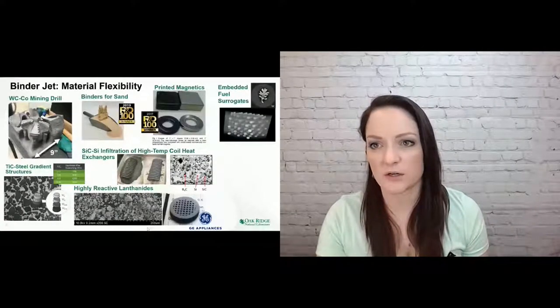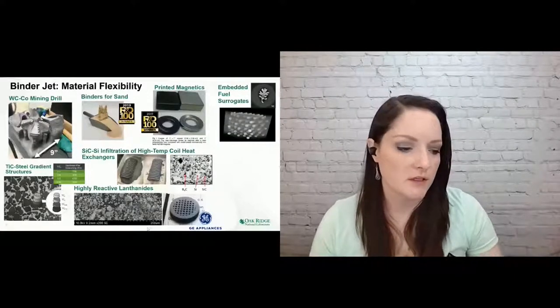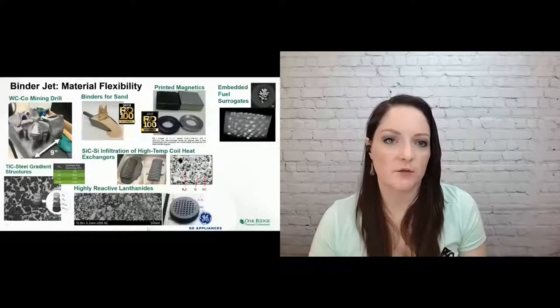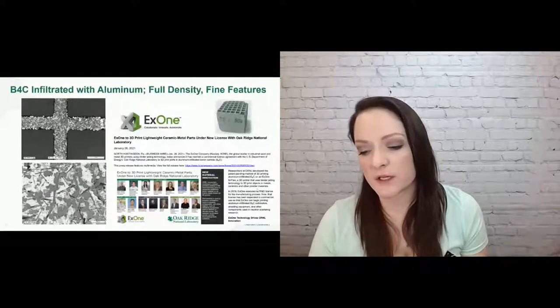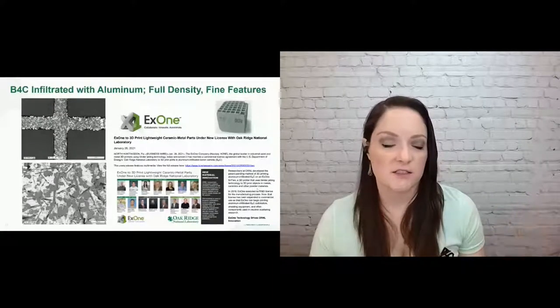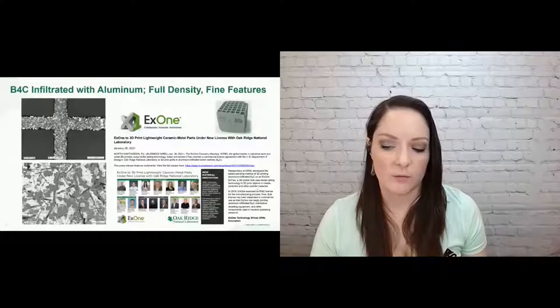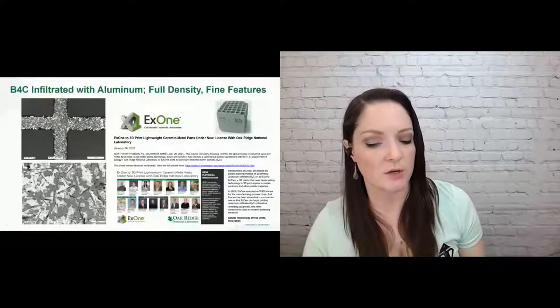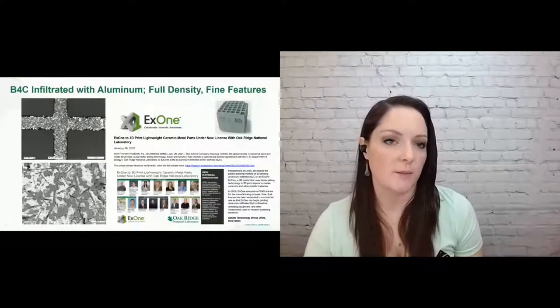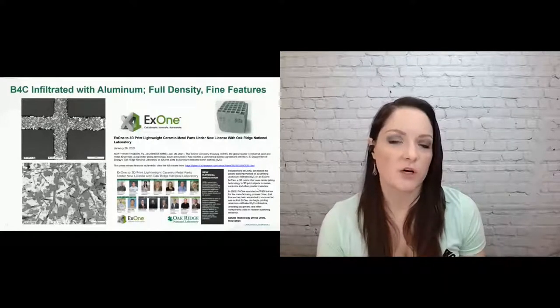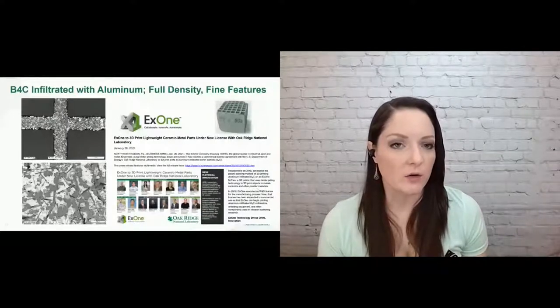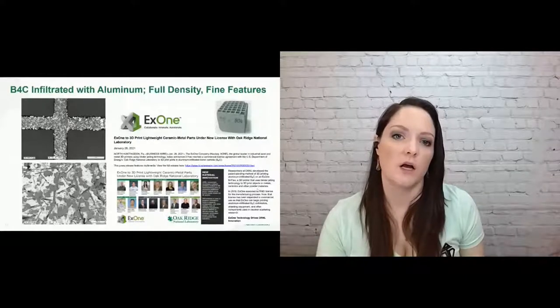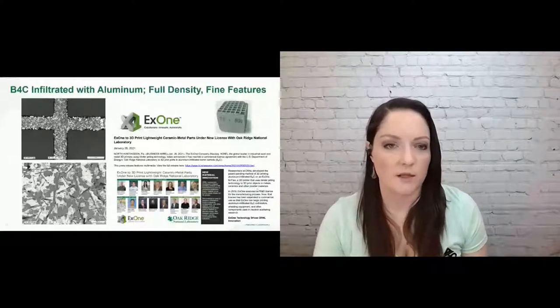So this is a cool little animation of our embedded surrogate fuels. Most recently we have been able to demonstrate the infiltration of printed B4C, which is boron carbide. It's a really great neutron absorbing material. So we have the world's most intense neutron beam. We were trying to figure out a way to print collimators or these absorbing geometries so that the scientists can get better data. And we figured out that we can not only print B4C, we can infiltrate with aluminum and make this actually kind of useful material with binder jet. It's a lightweight material. So just got that one licensed by ExOne. It was press release yesterday. I'm really excited about that material.